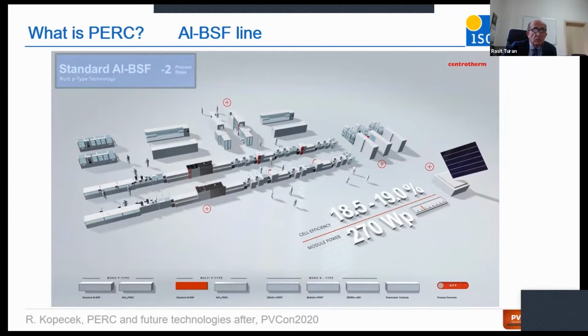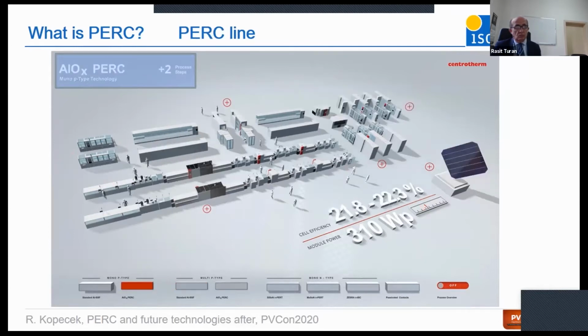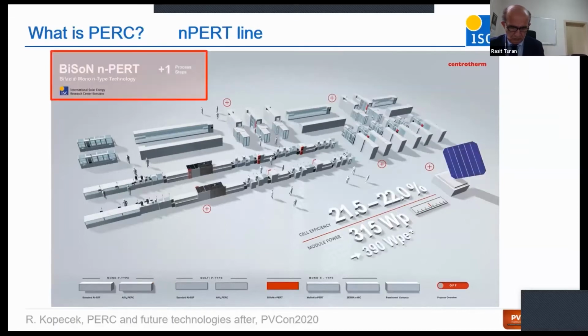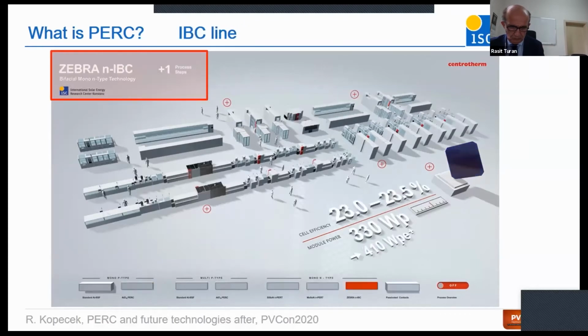And adding a little bit more equipment, we can then come to a PERC line, like adding lasers and additional silicon nitride machines, but also to N-PERT or TOPCon. And then you can even go to an IBC line when you are adding boron diffusions and silicon nitride and fast lasers for ablating the silicon nitride for masking and creating the P plus N plus region. So it's possible to produce an IBC line in the PERC line only with the upgrade of the line.